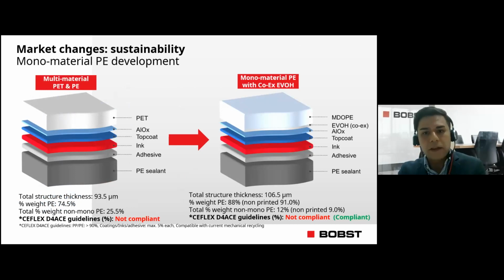Here we are presented with the dilemma visually of the mixed material structure, PET to PE laminate on the left, and on the right, the intermediate step of developing monomaterial PE. On the left, PET is coated with aluminium oxide or ALOX, a brittle ceramic transparent layer, which is processed on a vacuum metallizer. A barrier top coat is carefully prepared or applied on a coating machine with properties of protecting the barrier layer. Ink is reverse printed, typically with either CI Flexo or Gravure printing machines, and the PE sealant typically undergoes dry lamination, where the adhesive is either solvent or water-based.